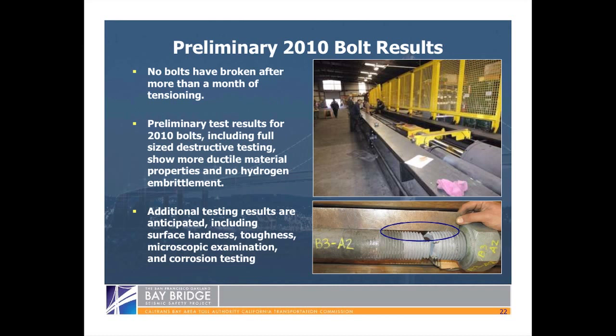That little break at the bottom, if you can see that circle there, if you remember the break that occurred on the 2008 bolts from a prior presentation, it was a brittle break, and it was fairly clean. You see here that this break is much, I won't say dirty because that's the opposite of clean, but what it reveals is something that pulls apart and is more ductile, more flexible, which is what you would like to see in this test, so that it's not as brittle, not as hard. We are also anticipating additional test results after today that will be going on for the next few weeks, and then there's another test that I'll describe that will take a little bit longer than that.